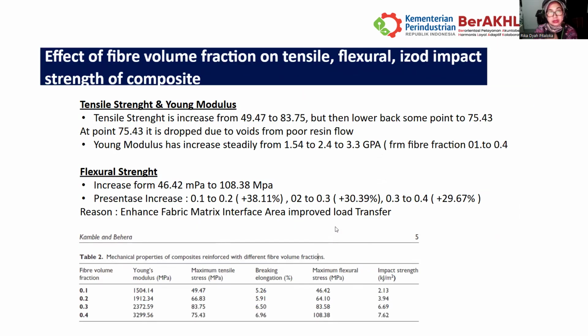Now we also discuss the effect of the fiber volume fraction on the tensile, flexural, and impact strength of the composite. For the tensile strength and Young's modulus, we can see the tensile strength starts from 49.47 for the fiber volume fraction 0.1. Then at 0.2, the maximum tensile stress is 66.83.